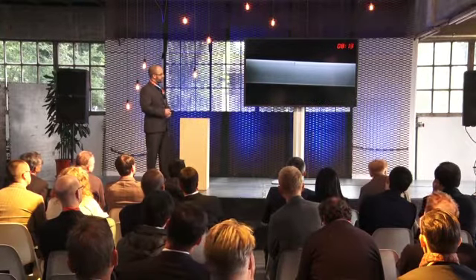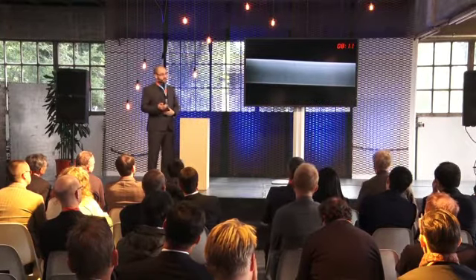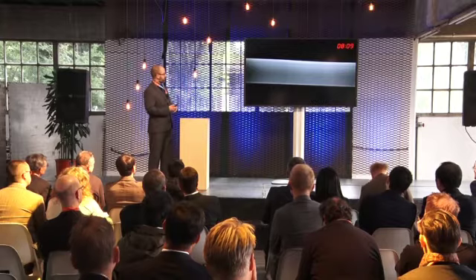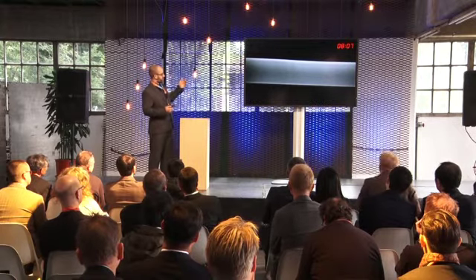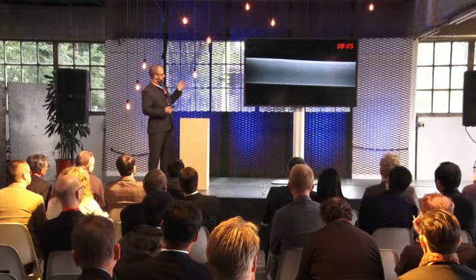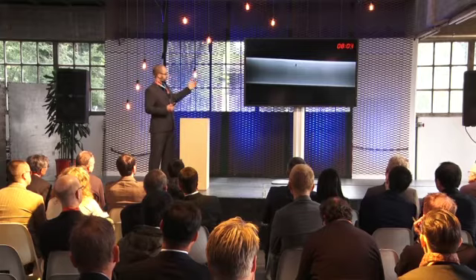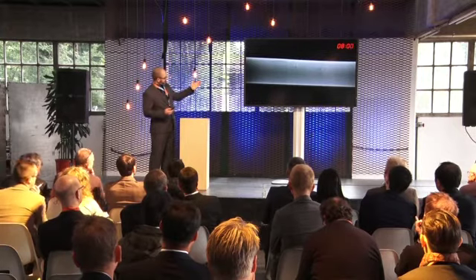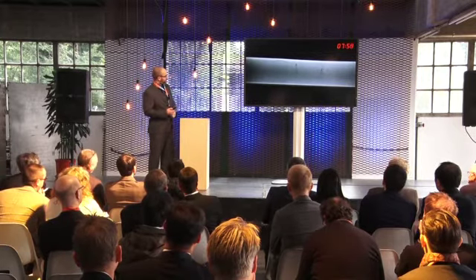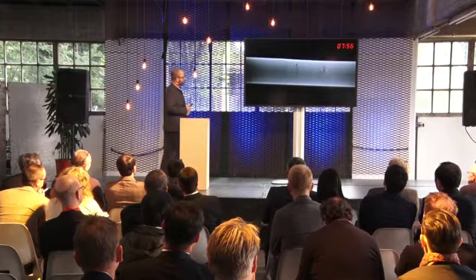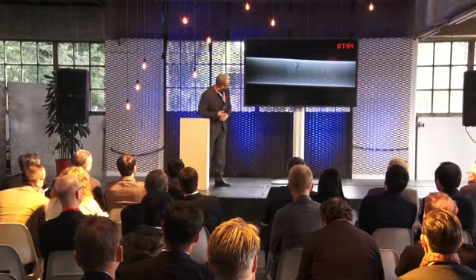So this is the raw data. This is what I see when I first get the volume. And what you're doing here is you're seeing the rail from a longitudinal direction, and you're traveling from the field side through to the gauge side. You'll soon see the triangular shadow that I showed you earlier. But what is worth taking note of is you'll get glimpses of something much deeper down.